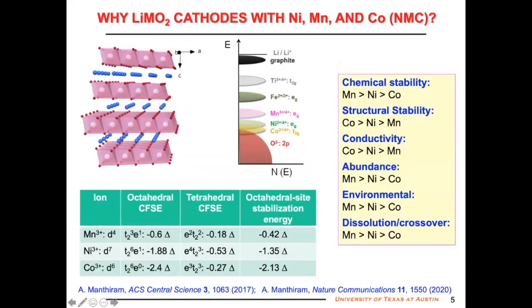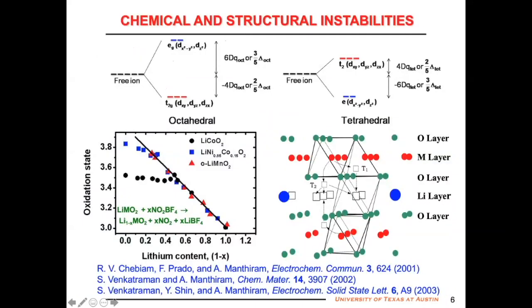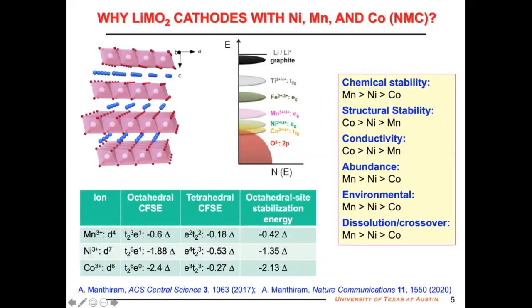The other factor is the stability of these ions in the octahedral site versus tetrahedral site. If you take the difference, that will be termed the octahedral site stabilization energy. As you see here, with the 6 electrons in the low-lying t2g band, cobalt 3+ loves the octahedral site, it hates the tetrahedral site. On the other hand, manganese has very low stabilization. It can move very easily from the transition metal layer through a neighboring tetrahedral site to the octahedral site in the lithium layer, transitioning from layered to spinel-like phases, voltage fade, all those which we do not have with cobalt. So cobalt is a gift.